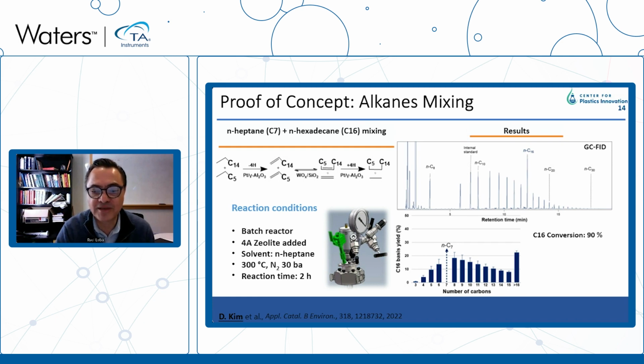Here at the bottom, you can see that we managed to have a 90% conversion of the C16 hydrocarbon product that we put in at the beginning. Again, we are not counting the C7 because we use that as the low molecular weight component of the molecular redistribution process. But you can see the molecular weight is centered around the molecular weight of the solvent, plus some extra amount, which is less than 25%, that contains molecules that are bigger than the reactant that we put in there.